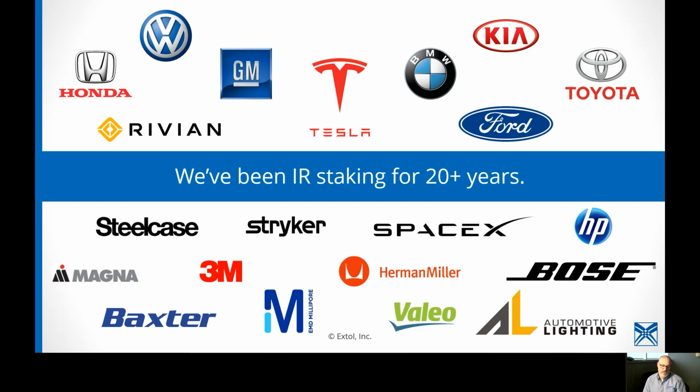Absolutely. And of course, if you do have different process parameters, your machine is only going to be as fast as the slowest part. We looked at that BMW engine cover a little bit ago. Some of those parts are black, some are gray. They can still all do them at the same time, but unfortunately the gray parts took a little bit longer to stake. So the black cycle time suffered a little bit. They were still able to gain cycle time because it was all done in one operation.